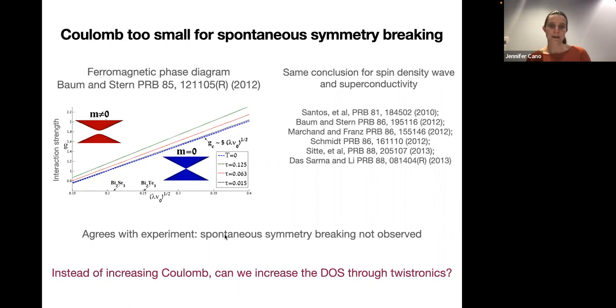Well, one thing we could do is to consider topological insulators that are made with more correlated atoms. But the other approach, which we're going to take, is instead of increasing the Coulomb interaction, can we increase the density of states in some way? And the way that we want to do that is by applying Twistronics. So I showed you in graphene how the density of states of graphene gets severely enhanced by twisting the two layers. And so the question is, is there some similar thing we can do to the TI surface that will increase the density of states and thereby push us into this regime of gapped, spontaneously broken symmetry surface states?